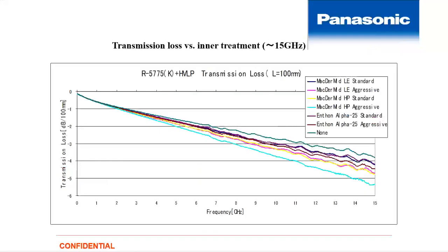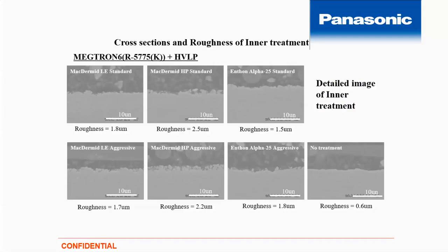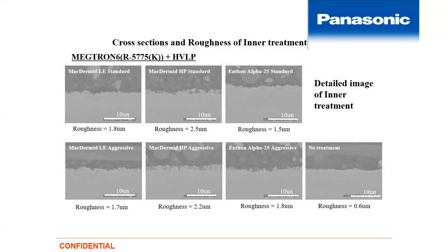Again, this is just another breakdown comparing different oxides. And the point being here is that the none value, where there's no oxide, actually has the least amount of loss compared to anything that roughens it up, and it gets the highest. If you have a very aggressive oxide, then you get more loss because of that. There are a lot more oxides in the market, and the point is that oxide matters and we need to categorize that. And it kind of fits that the rougher, more aggressive ones, you can see the topographies on them, are the ones that actually have the highest loss. So that's the impact of the copper roughness, and also the oxides, on signal performance.